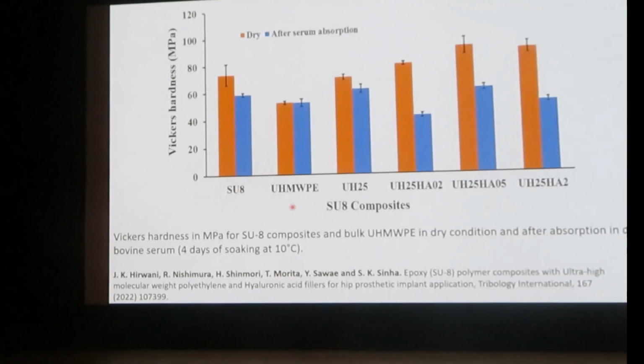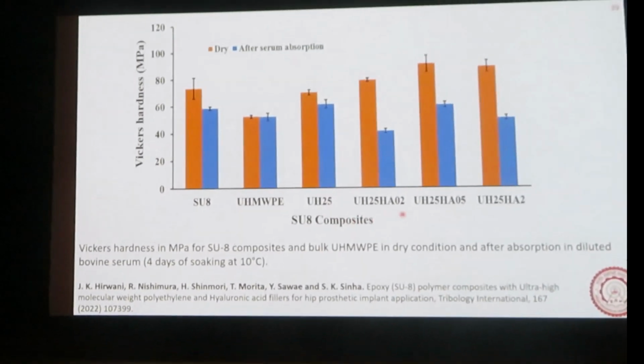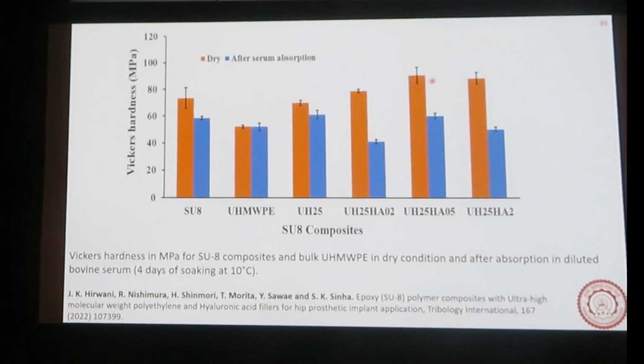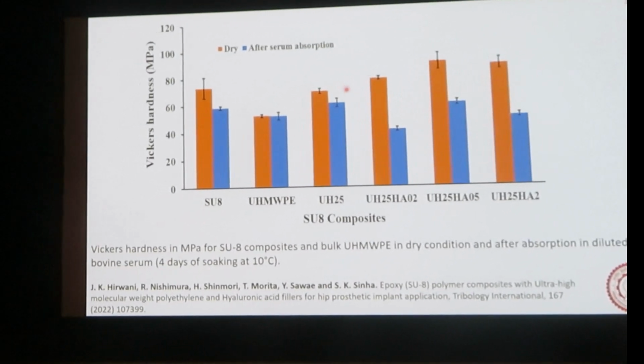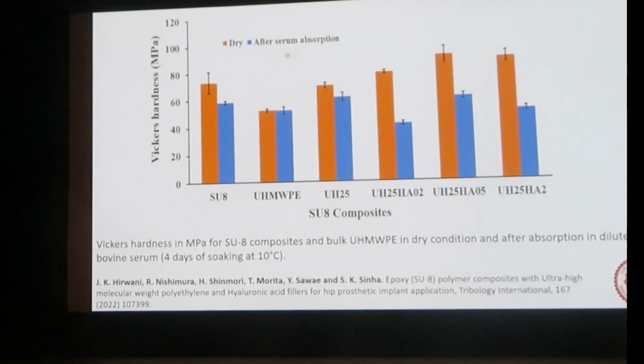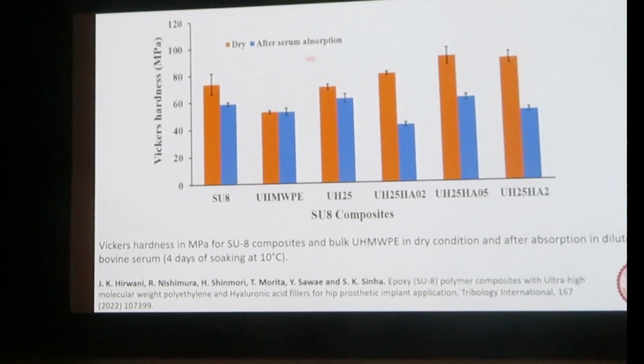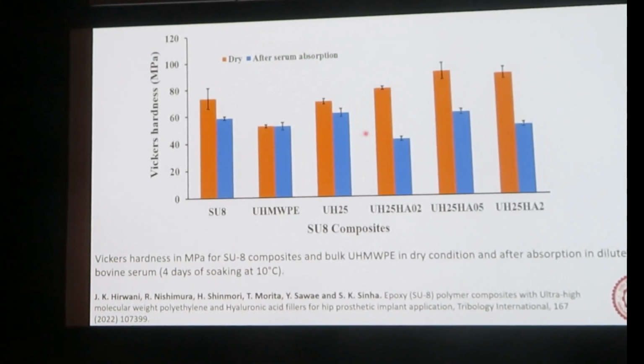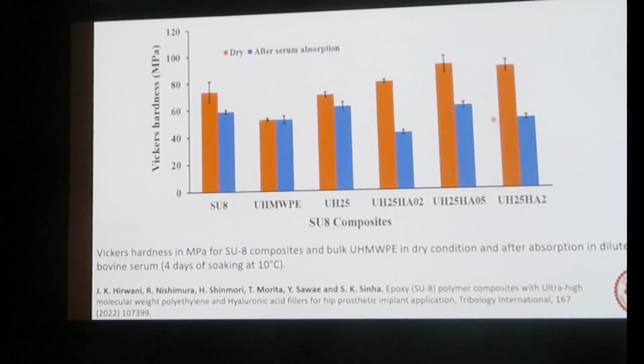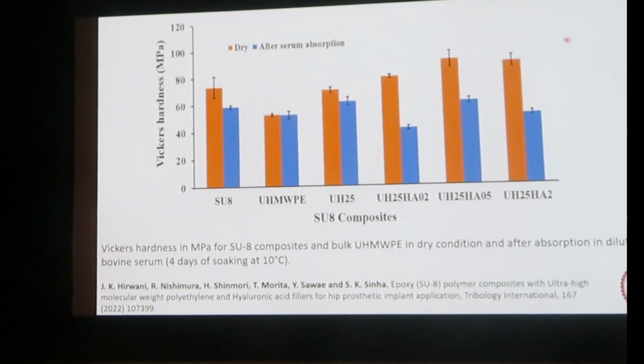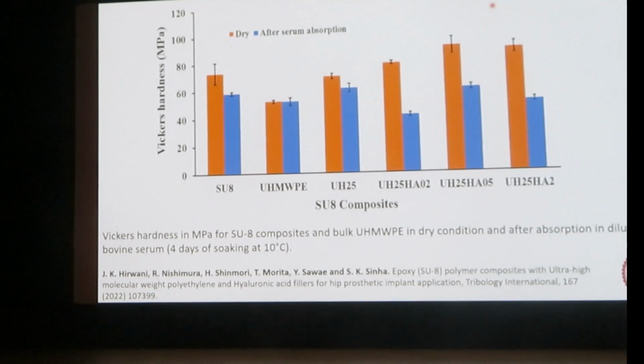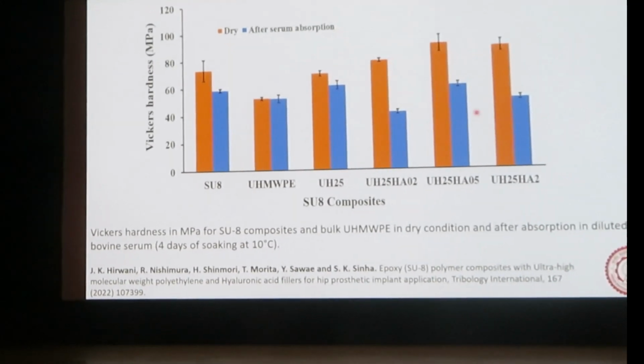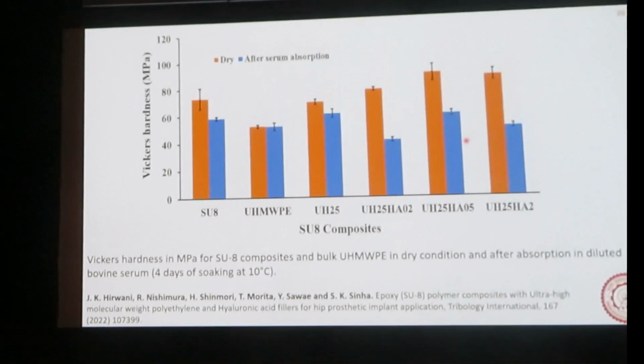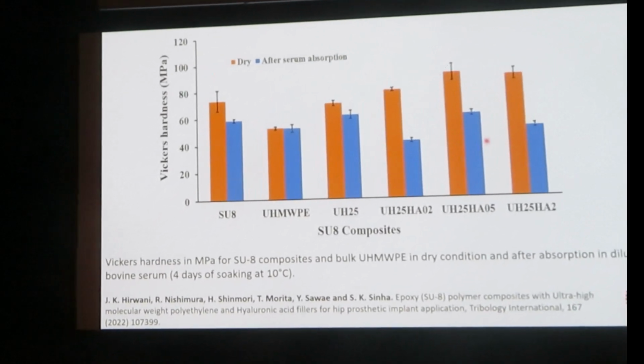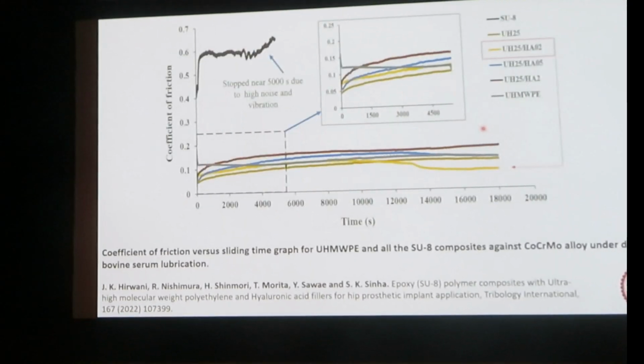First is the Vickers hardness test. Adding these fillers actually improved the hardness to some extent in the dry case, but if we soak the specimen in bovine serum for some time, the hardness actually reduces. So there is a complex behavior here of this composite, the epoxy and the filler: hardness will reduce if it is soaked in bovine serum solution for some time.